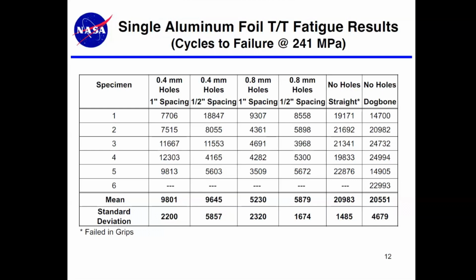And I point to the bottom of the second column, the mean number there, 9,800 cycles to failure for a foil that has 0.4 millimeter holes and 1 inch spacing. And then across the right-hand side, second column from the end on the right, the no holes straight is the top of the column. The number there is 20,983. So essentially the holes cut the cycles to failure in half compared to what would be considered a pristine sample.